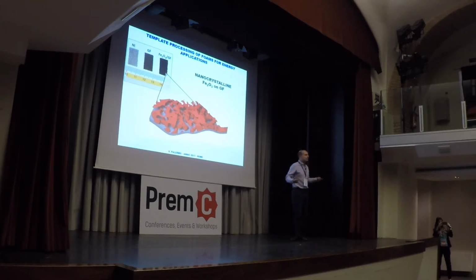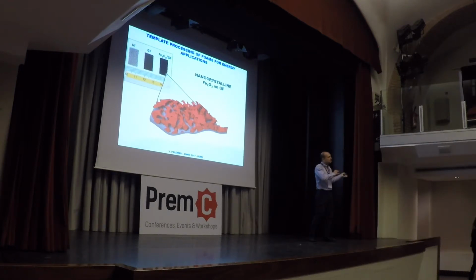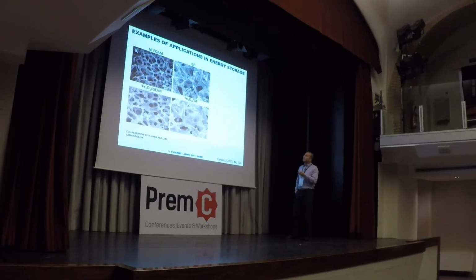Here I used the metal foam, but people are really using anything, polymer foams, even oil-water mixtures. You can have graphene oxide going at the interface between micelles, then remove the liquid, and you have, again, foams that can be flexible, can have different kinds of properties. That is the concept. This is the initial nickel foam. This is the nickel foam coated with graphene flakes after you have removed the metal, and you can see that it really follows the structure nicely. And this is the final result.